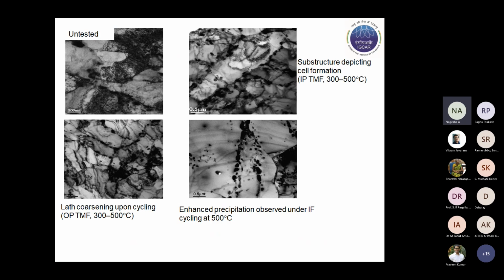So this is a typical substructure. As I said in the earlier slide, the martensitic lath structure in the untested condition can be seen, whereas it gets restructured, and subcell substructure formation happens under IP cycling, and coarsening of the laths happens, and enhanced precipitation is also observed. These are probably the prior martensite laths, which are replaced with a lot of precipitation happening inside.